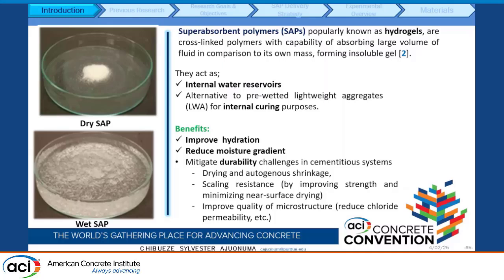From past research, we found out that some of the benefits include improved hydration. They reduce the moisture gradient in concrete, and most especially, they mitigate certain durability challenges: autogenous shrinkage, drying shrinkage, and scaling. And they also help to improve the quality of the microstructure of the concrete.